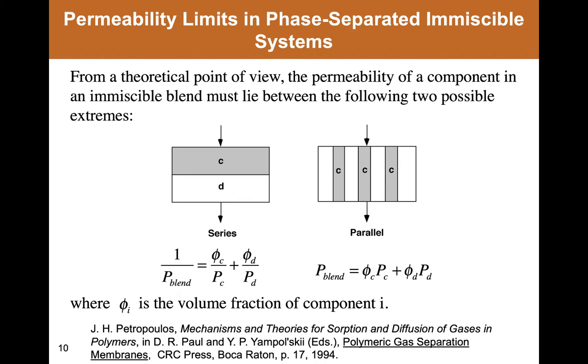And so, for example, there are two limiting theoretical models that describe how the transport properties of a blend of two materials can change with composition. I won't go into detail yet, but I'll show experimental data in a moment. You can show that the permeation properties of a blend of two materials has to always lie between the limits in transport that are shown on this slide.